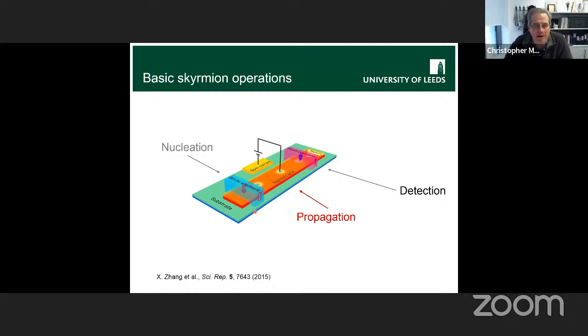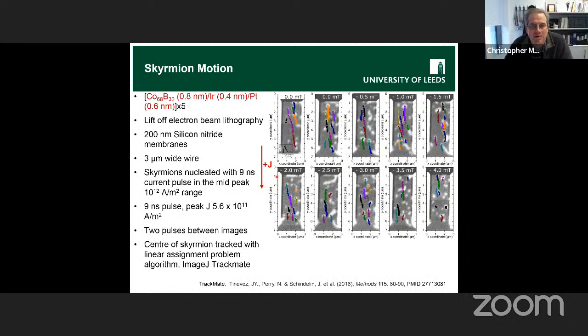The next step in our racetrack frame of thinking is propagating skyrmions around. Here we've got a similar structure, actually. This experiment is older than the nucleation one. This is a 3-micron wire, exactly the same, but it just has flat contacts at each end. There's no nucleation finger. But what we found we could do was, if we put in a moderately strong current pulse, we could fill it up with skyrmions. That's what all these little patches of bright contrast are that appeared in this wire.